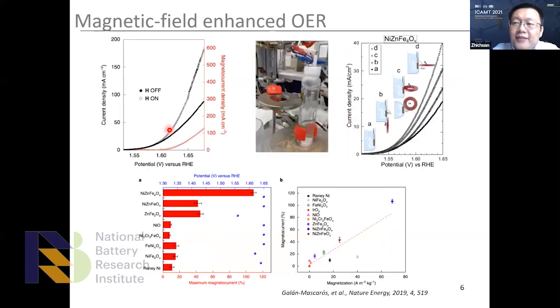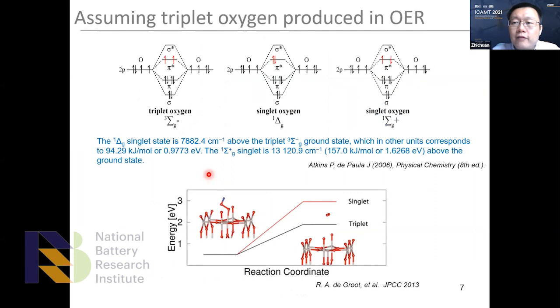And recently, a very, very interesting phenomenon has been reported a couple of years ago, and we actually found it as well. This phenomenon is that a magnetic field can enhance the OER. If you apply a magnet on the working electrode, you will see an increment of your OER current. So the reaction kinetics actually gets promoted, right? This is a very interesting phenomenon.